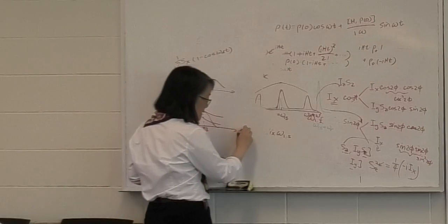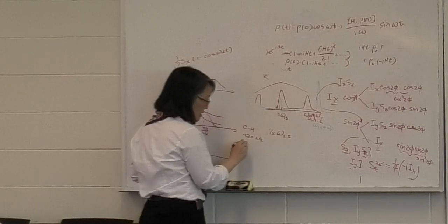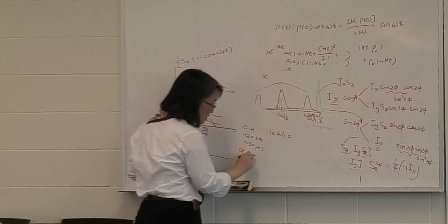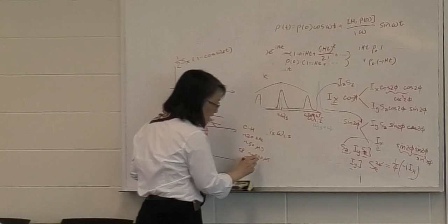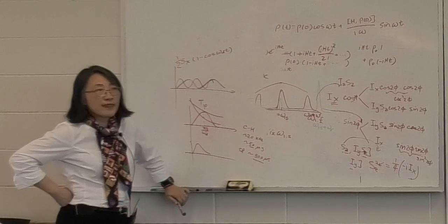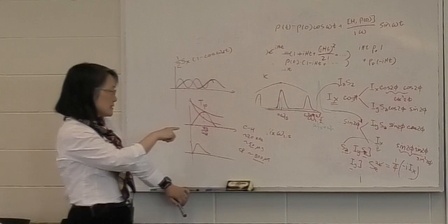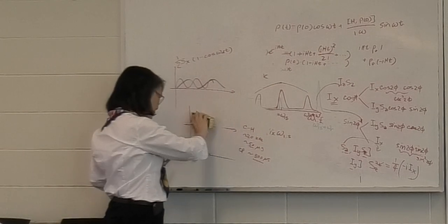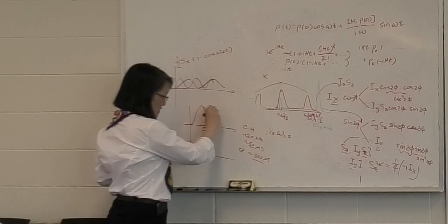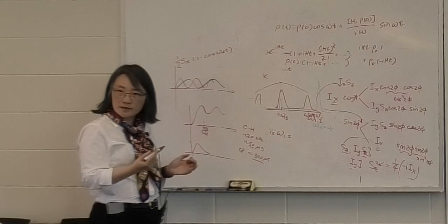Okay, so let's say for a CH bond of 20 kilohertz or so, close enough, 23 kilohertz, the inverse is 50 microseconds. We usually do CP on the order of, let's say, 500 microseconds. So we actually go long enough compared to what the coupling strength would dictate. But there's a powder averaging here. So you can actually see this effect. We can actually see oscillations under the Lee-Goldburg CP. Looks quite nice. And so you do see it oscillating experimentally.